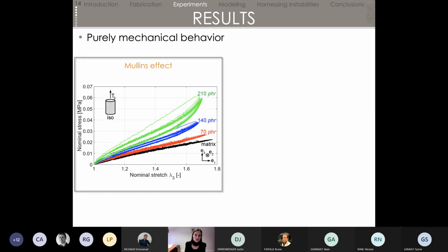So we started obviously just with purely mechanical tests. We see fairly classical results, which means that if you plot stress versus stretch, a pure matrix is obviously softer than when you put more and more particles in your composite material. So you see the stiffness increasing with the particle content. Because we have a composite with particles inside, we have the Mullins effect, which means your first loading will look different from the other ones. It corresponds to the fact that your particles are going to break some bonds permanently with the matrix. But after a few cycles, you will stabilize into a hysteresis that's going to remain the same. And of course, the more particles you have, the larger your hysteresis.